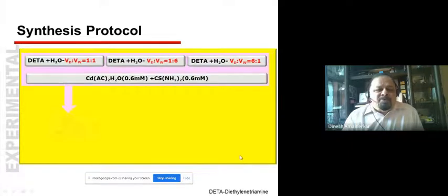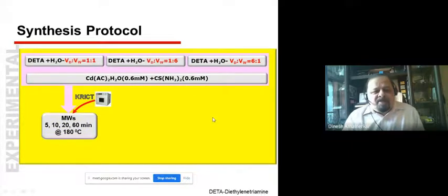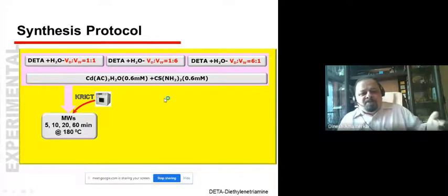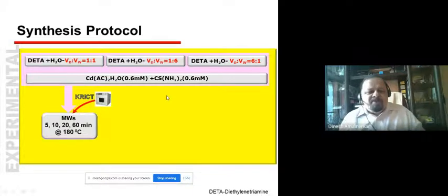So this is a typical synthesis protocol. We have mixed cadmium acetate and thiourea in certain millimolar ratio in a binary solvent mixture of diethylene triamine and deionized water in different ratios. This work was done way back in 2007 at the Korea Research Institute of Chemical Technology. Then this mixture was transferred to a Teflon-coated autoclave, that is our pressure cooker, which is placed in the microwave digester. There is a very good microwave digester with a lot of controls available at Korea Research Institute of Chemical Technology, where my Korean students had worked on that.